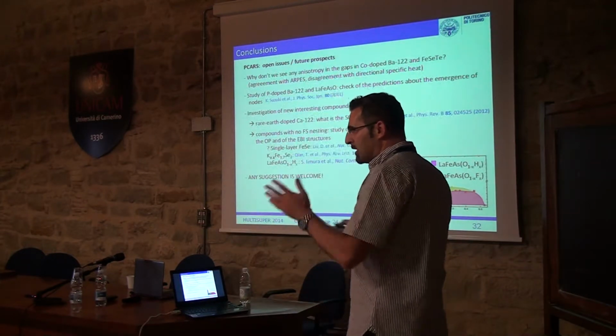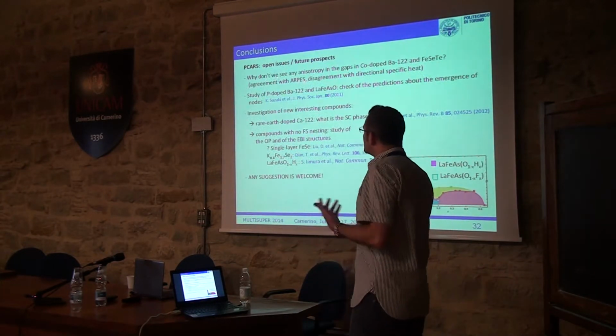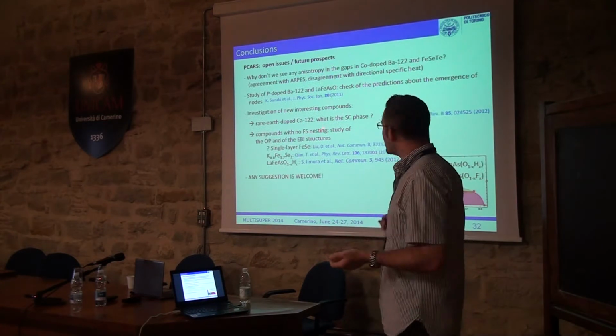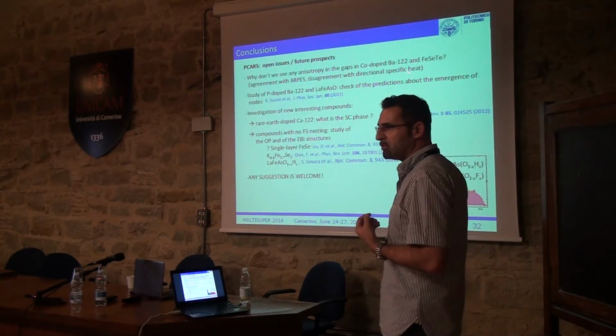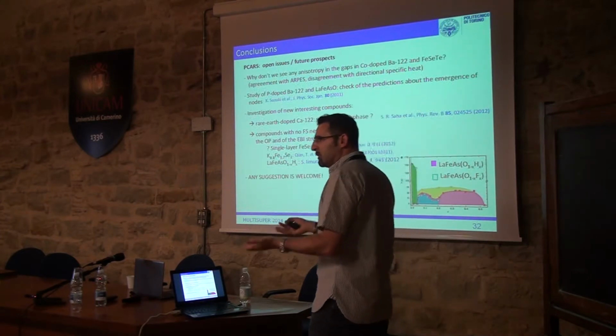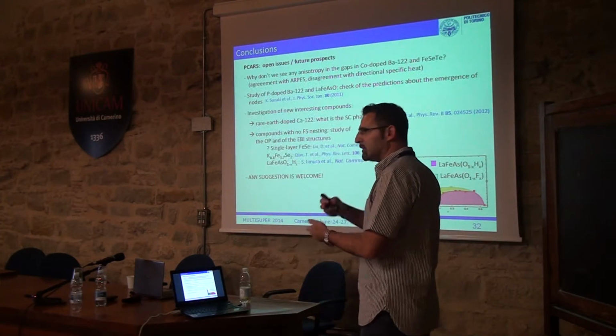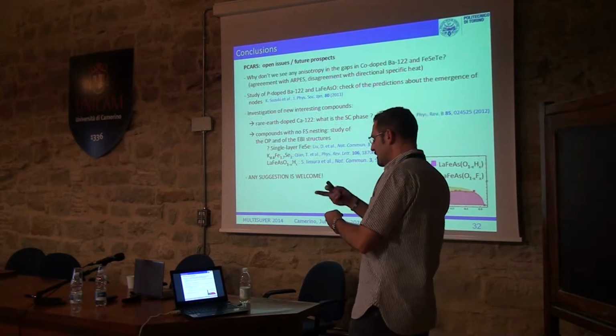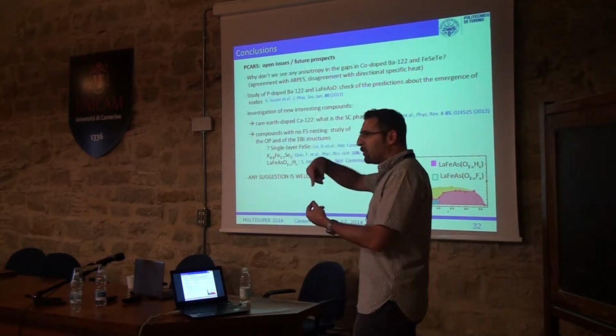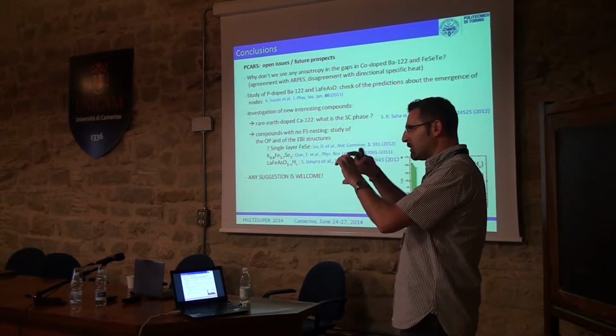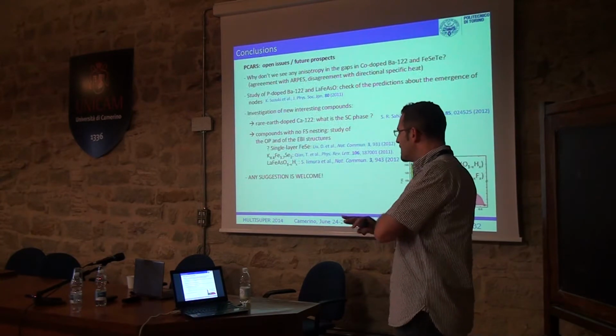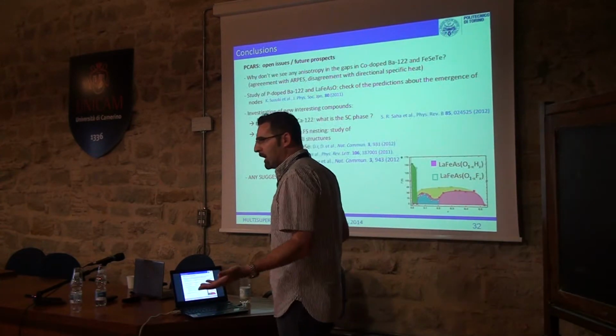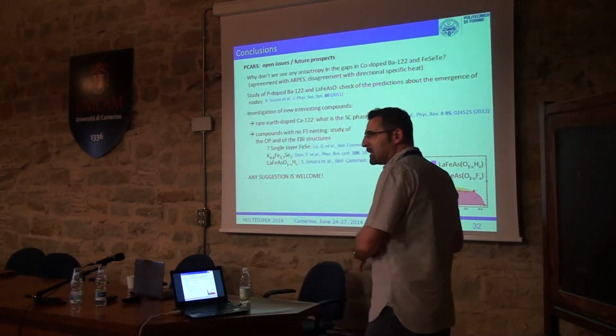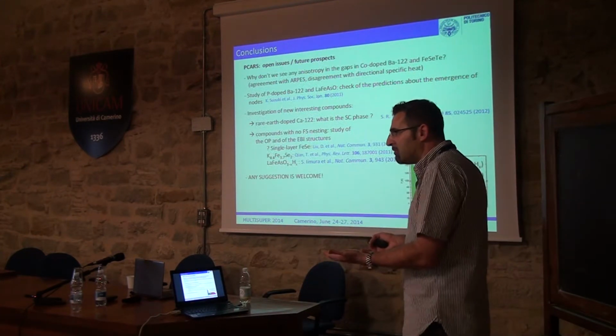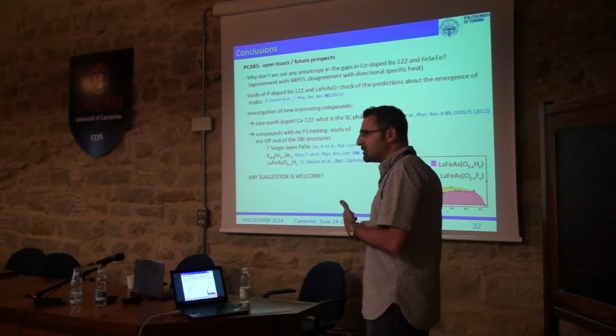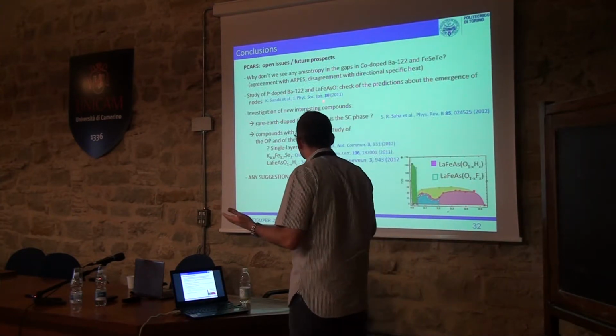Okay, open issues, there are many open issues. The first is, why don't we see any anisotropy in the gaps? Also in cobalt-doped barium 1-2, many measurements, for example, the measurements of Raman scattering, directional specific heat, see fourfold oscillations or loops of gap minima. We never see something like that. We don't know why. Either our technique is not sensitive enough, but also ARPES, for example, does not see any oscillation. So this is an open question.